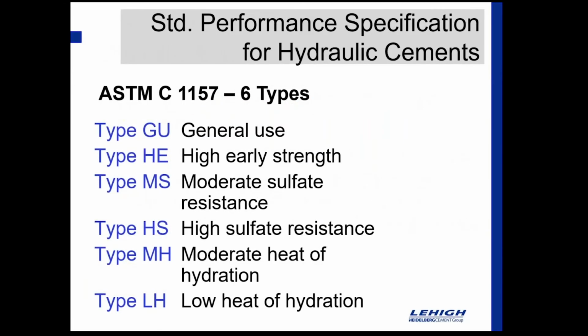And so again, we have our 6 types. We've got type GU, which is general use. And what you begin to notice is that the 1157 cements kind of have their C150 counterparts. So type GU general use is roughly equivalent in terms of performance to just our everyday type 1 cement. Type HE, high early strength, again, similar to the performance we would get from type 3 cement. Type MS, moderate sulfate resistance, and type MH, moderate heat of hydration. Again, that's your type 2 cements and so on.